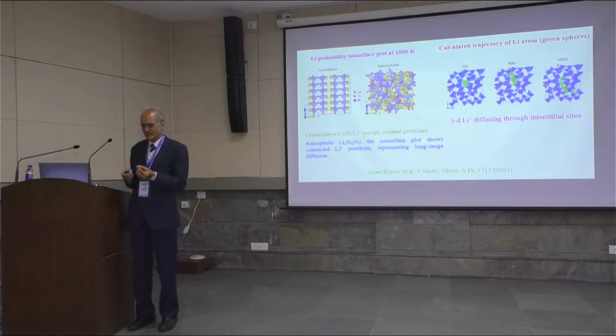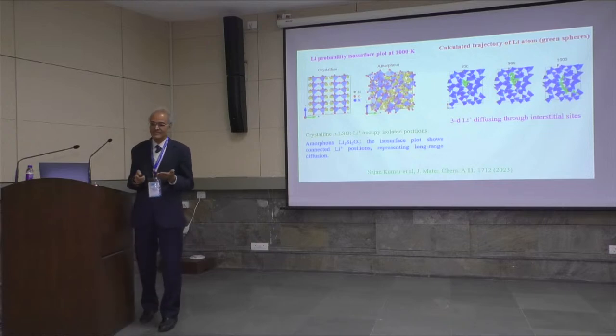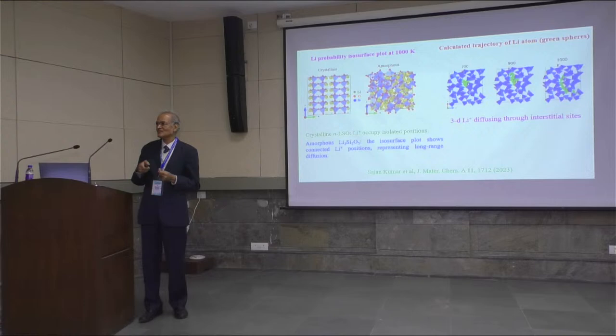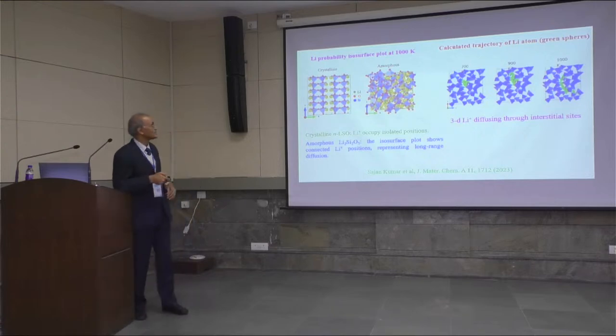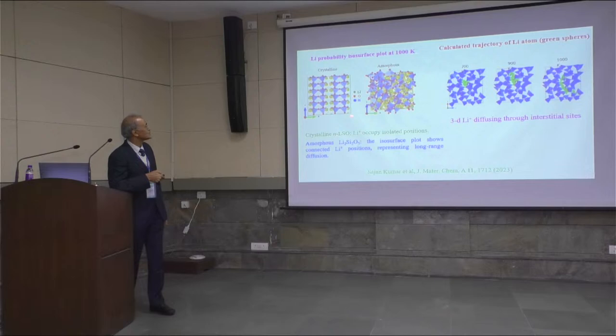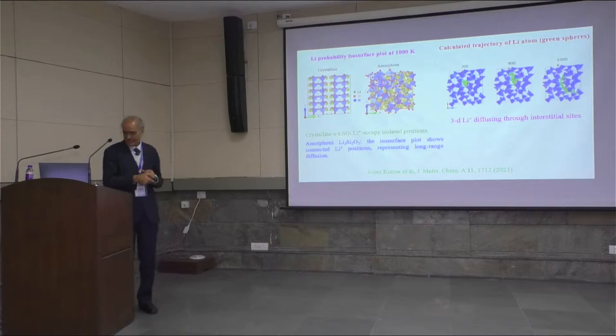But in simulation, the typical time step at which the atomic trajectories have to be calculated has to be a fraction of a picosecond. Precisely for that reason, if you increase the temperature, then you can accelerate the process. So it was just done artificially. This way one can identify or calculate what exactly is happening at the microscopic atomic level.